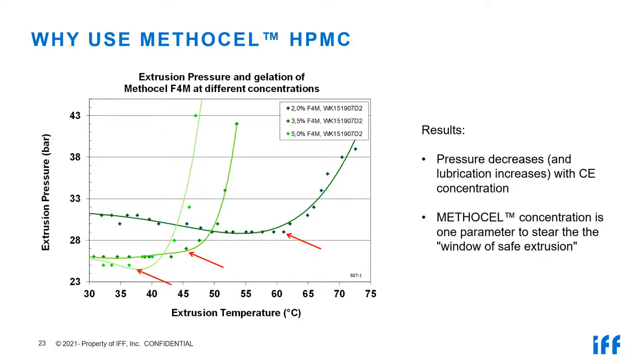gelation temperature drops from roughly 60 down to roughly 45 centigrades. This means your window of safe operation is reduced by 15 centigrades. This is a lot. If you have difficulties in cooling, this might be hard. And example number 3 with 5% of F4M, you can get still a little drop in the extrusion pressure, but this is not significant anymore. However, you get also a further drop in the gelation temperature.